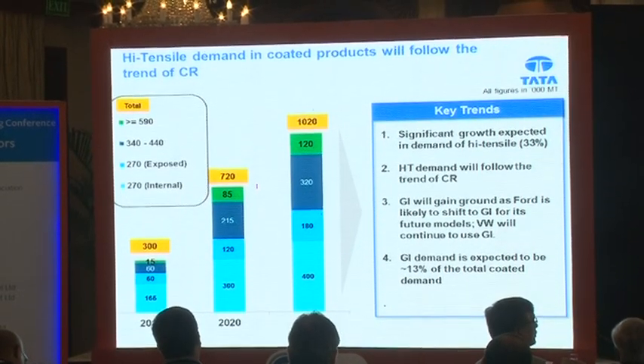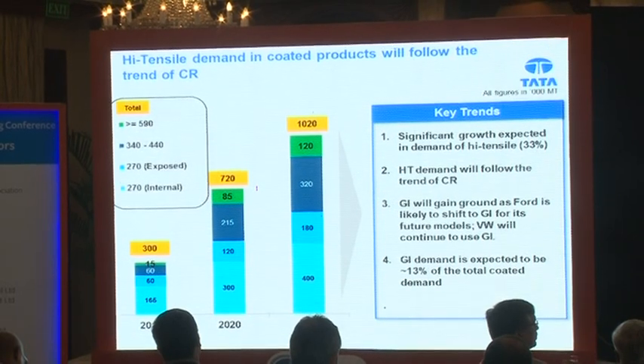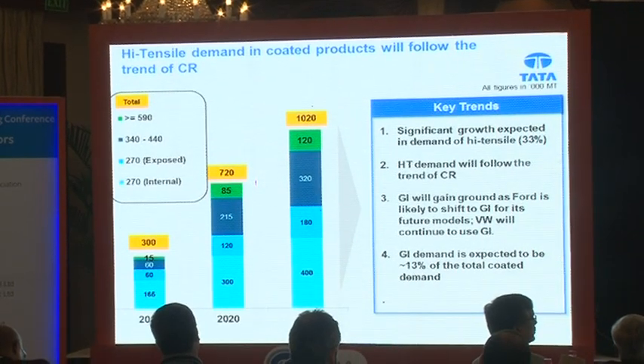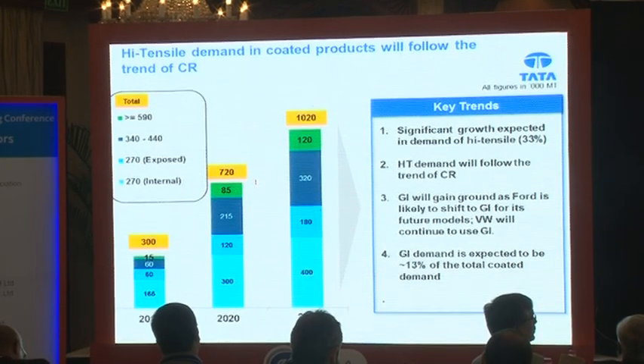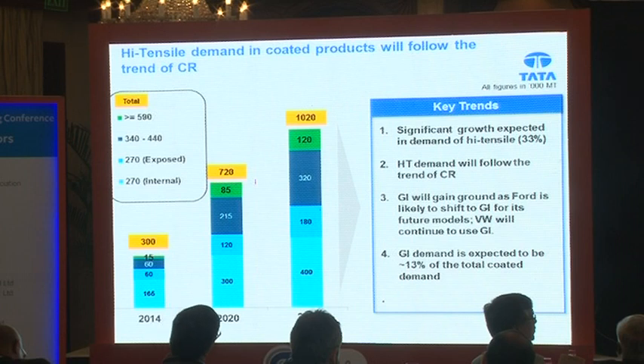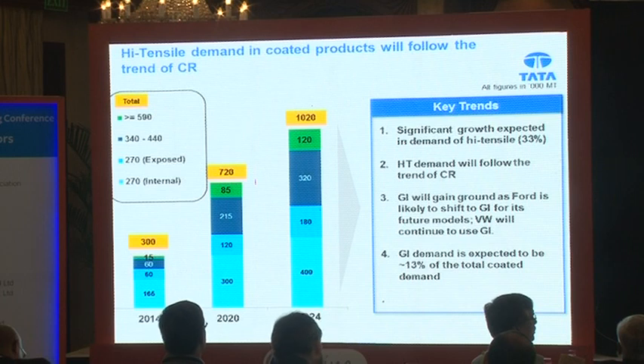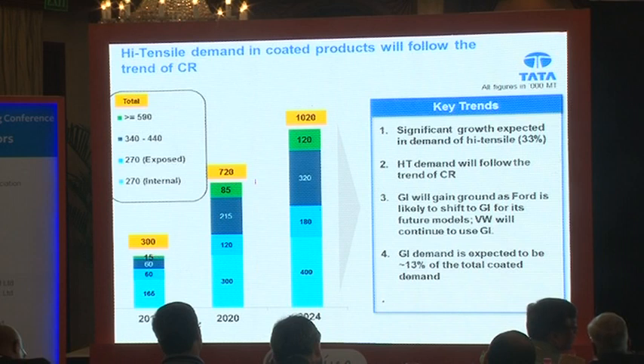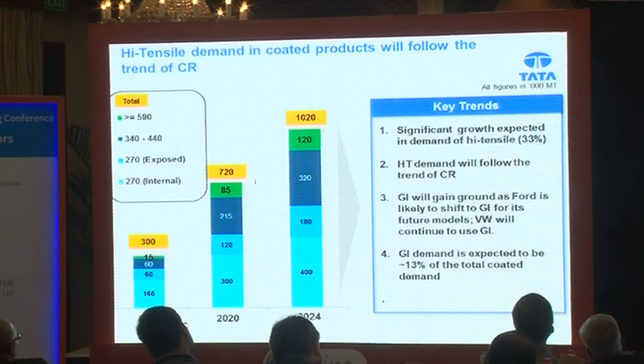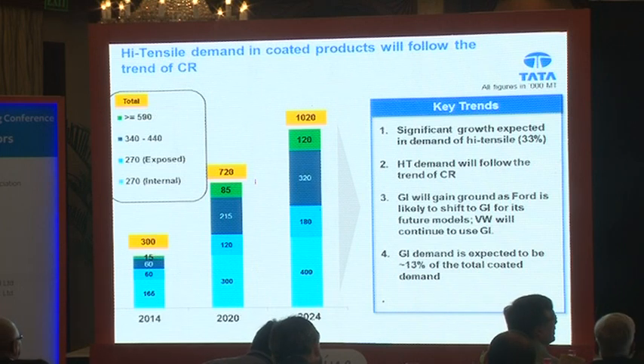So, typically, like what Ken mentioned, for skin panels people used to use only very soft steels. Now people say, no, we want to use high strength steels. I can tell you, about 10 years back, the door of the car was made from 0.8 millimeter. Now people have come to 0.65. Safety has not been compromised. It is just that high strength steels have started to be used, and the demand for high strength steels will continue because cars will have to be made safer. You have to have less GHG emissions in the cars.